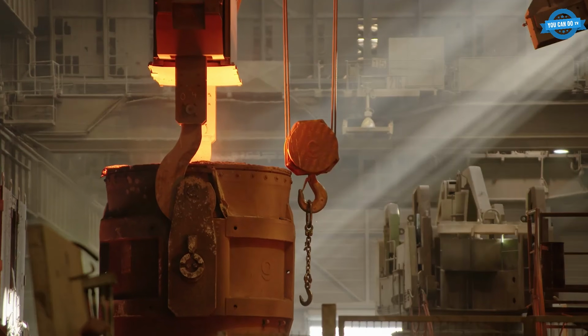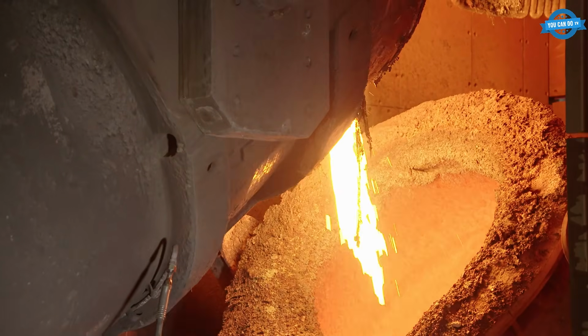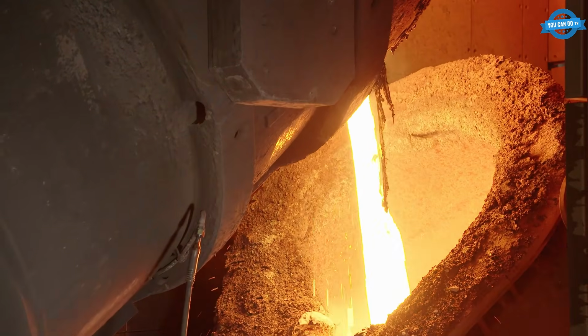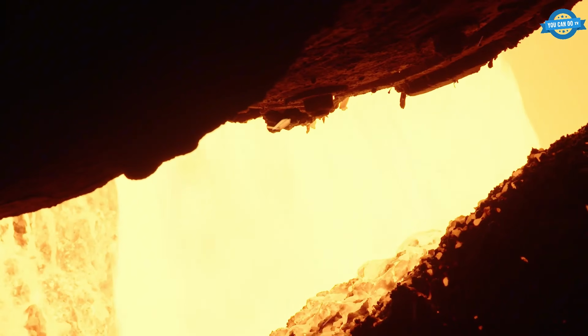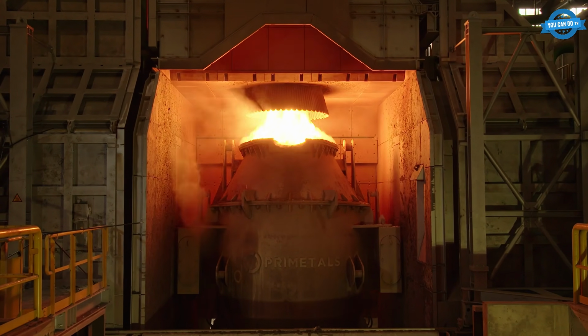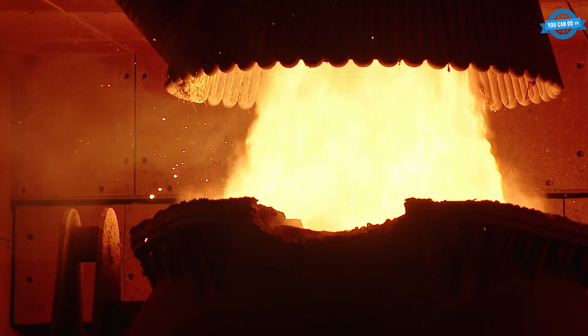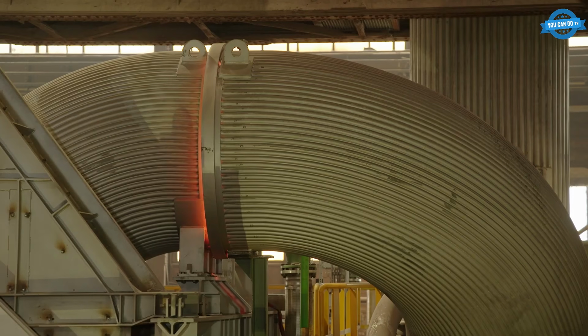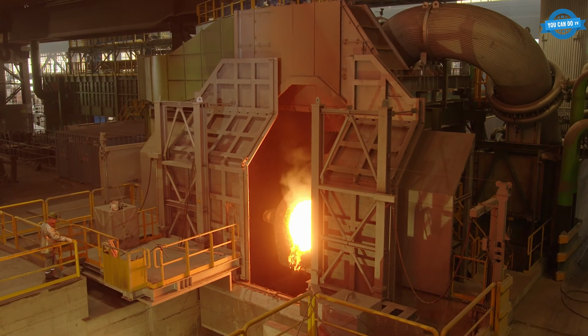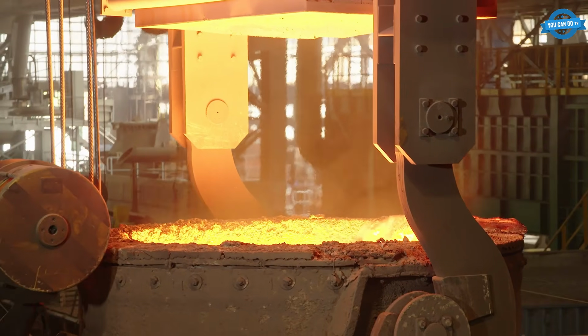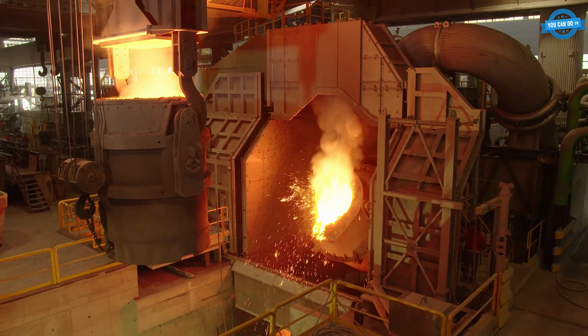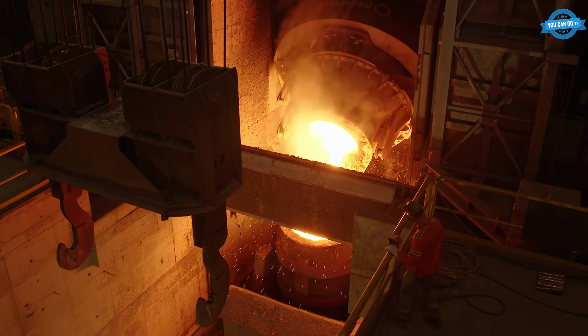After the primary melt, the steel gets fine-tuned. In a ladle furnace or an argon-oxygen decarburization vessel, operators inject gases, add trace alloying elements like manganese and vanadium, and adjust chemistry until the grade matches the buyer's exact specification. Milligrams of a rare element decide whether the steel goes into rebar or a jet engine.